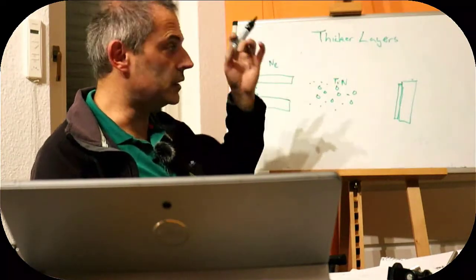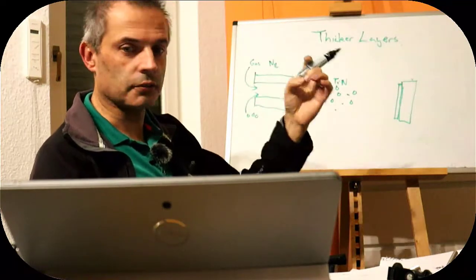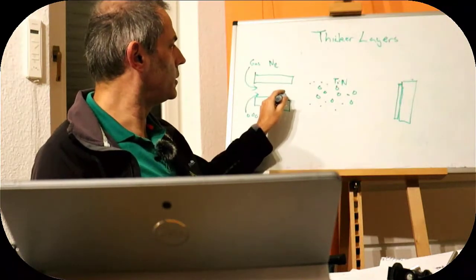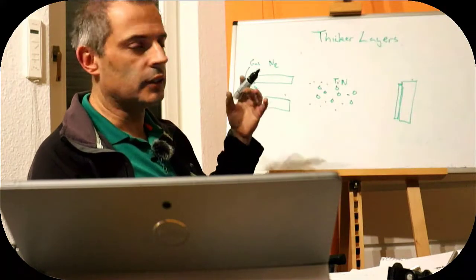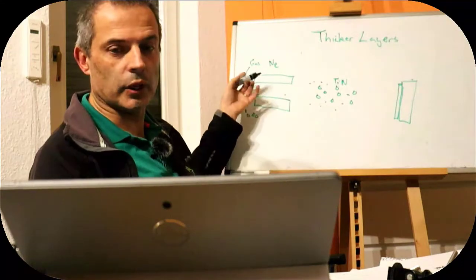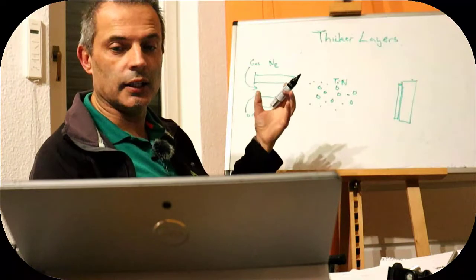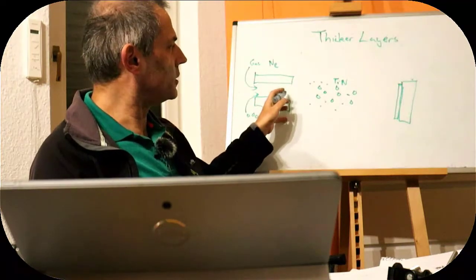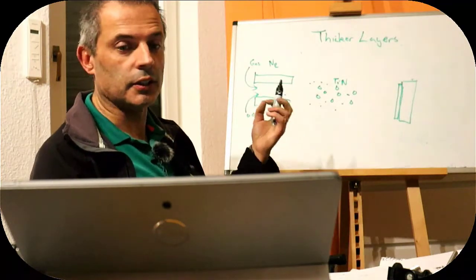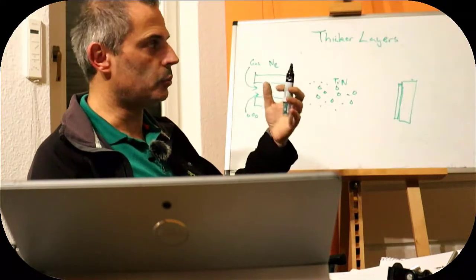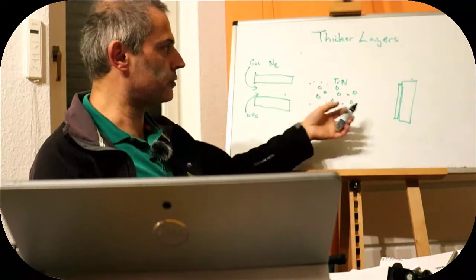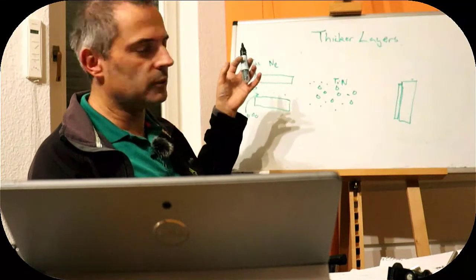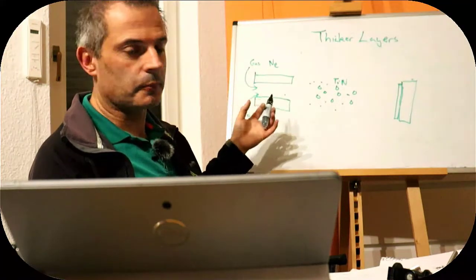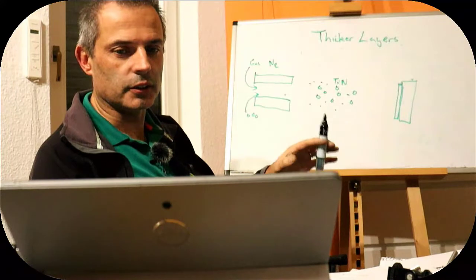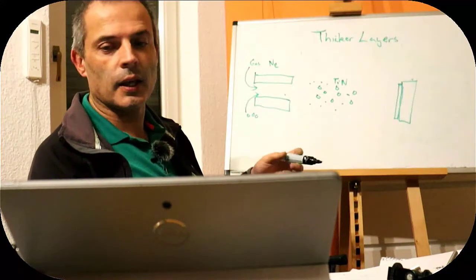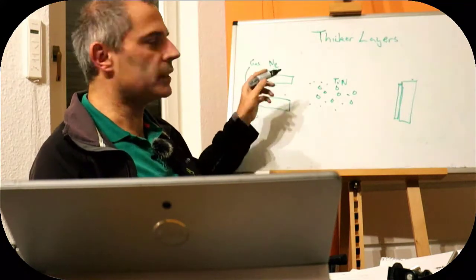So the probability of the gas hitting the surface of our particles up here in the front part of the barrel is very low. The probability of hitting it where the pressure is higher at the back is good, but the probability of gas molecules hitting the surface of our solid further up is low, because although the pressure is still atmospheric, the temperature is very high, and so then the density of gas molecules drops. Here our nitrogen comes in very handy.